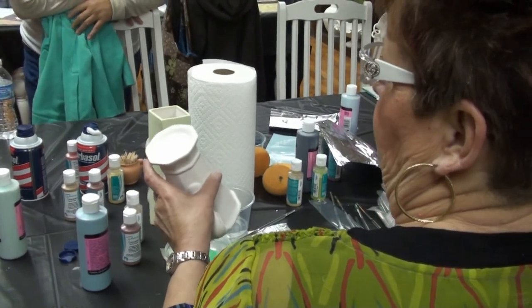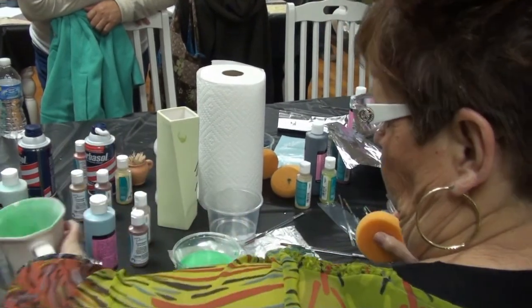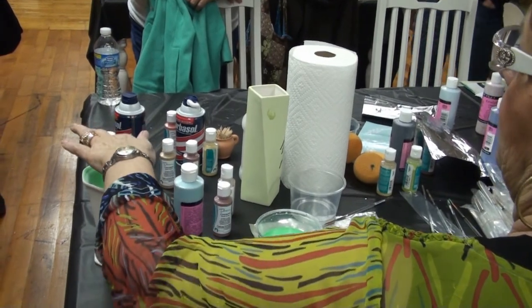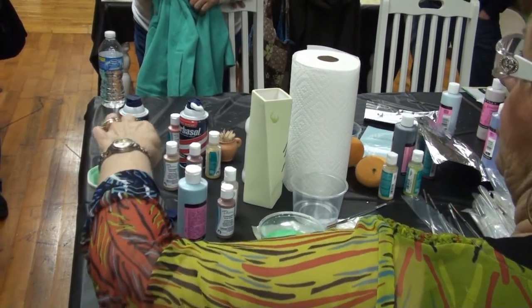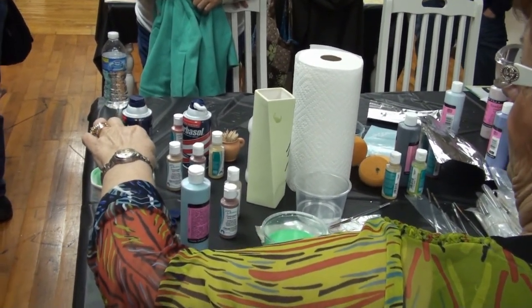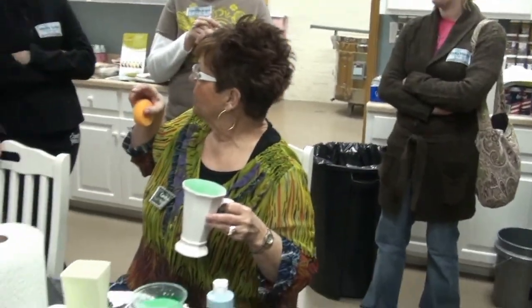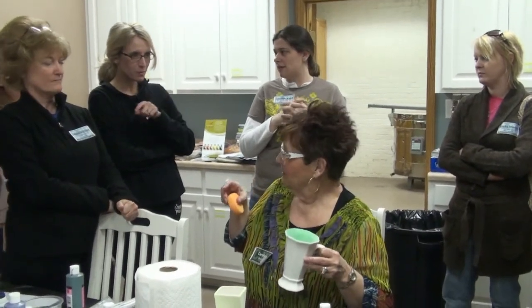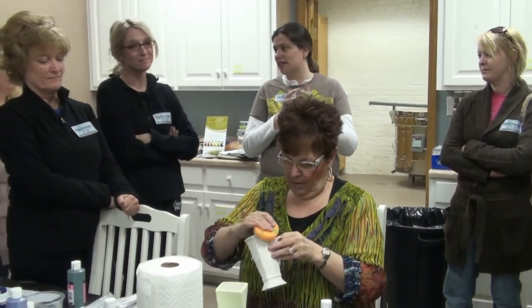Whenever you dip this piece, a lot of you, or your people that are dipping for you, have a real bad habit of doing this and going to the next item. What happens is if you turn this up while it's still wet inside, all the excess glaze is going right to the bottom. And that's what causes you to get crawling down at the bottom of your pieces. Anybody had that? What's crawling? Crawling is where the color crawls away and leaves bisque. It's too thick, so it pulls away when it fires.